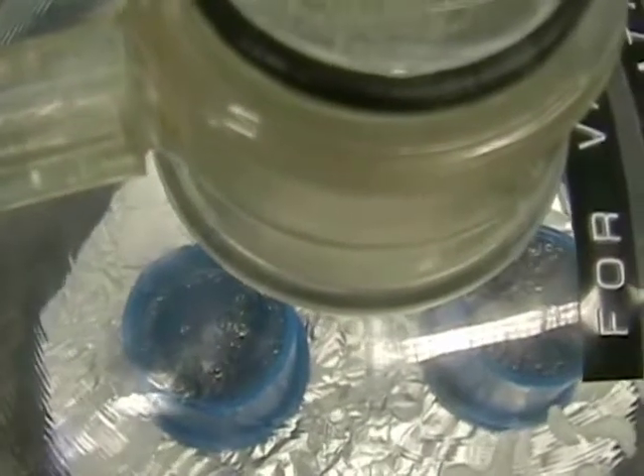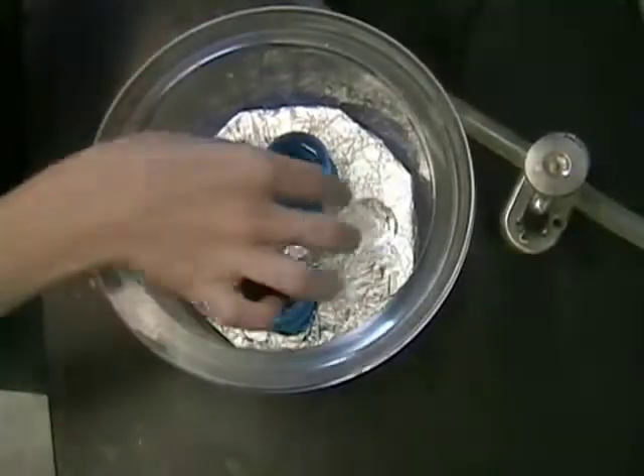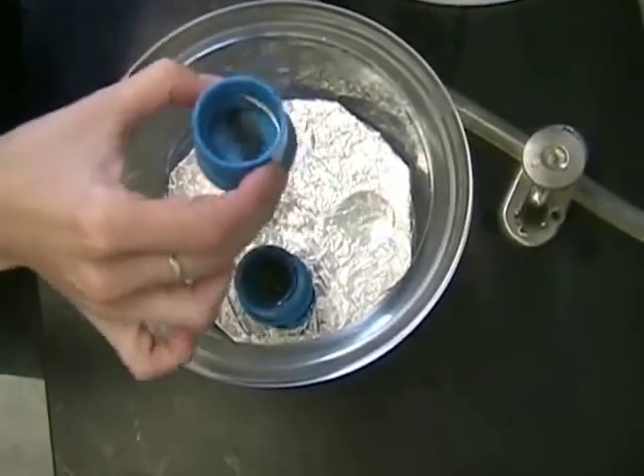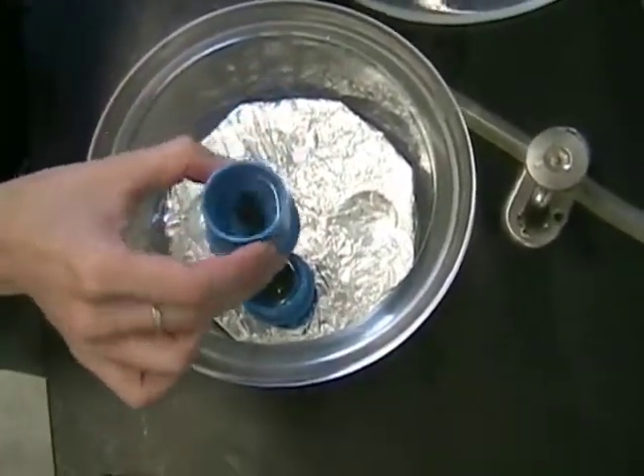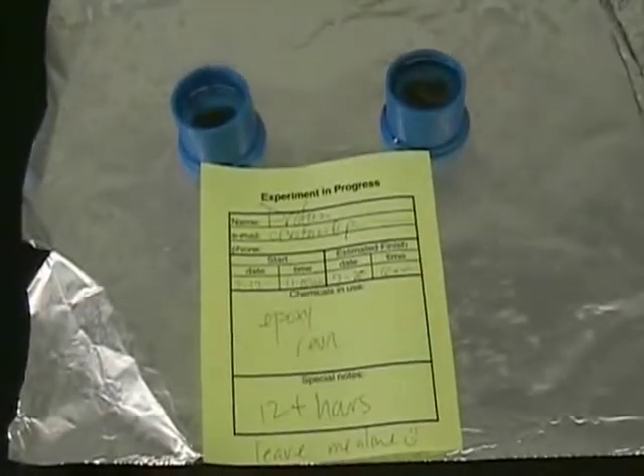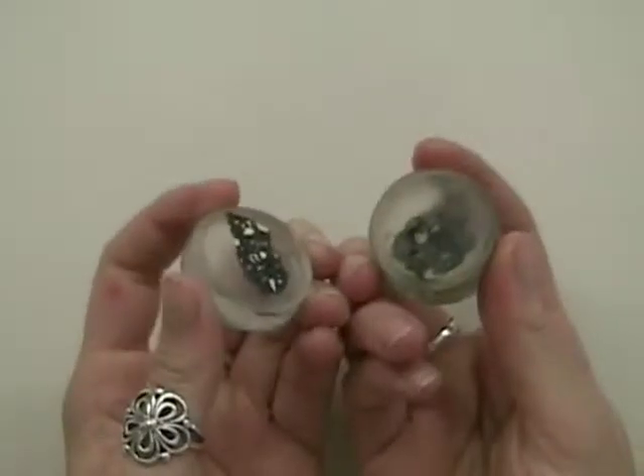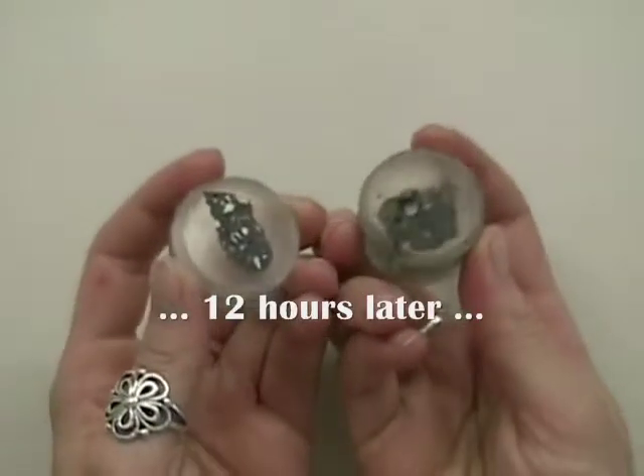and here you can see the air bubbles rising to the surface and popping, and this is after about 10 minutes of vacuum where there's no more bubbles and the epoxy is very clear. This particular epoxy sets in about 12 hours. This is a finished epoxy sample with beveled edges.